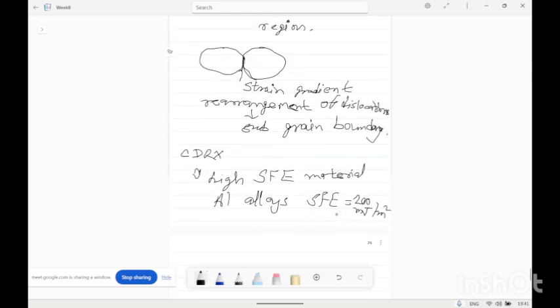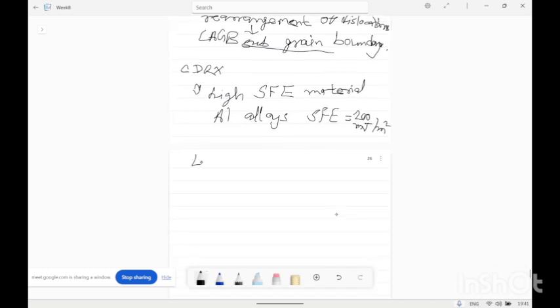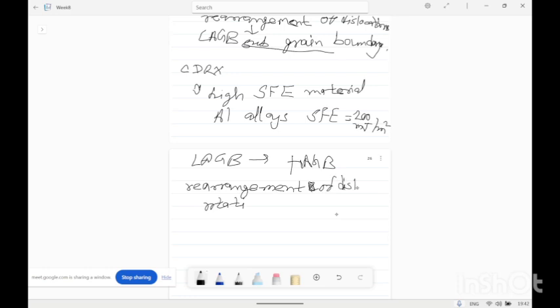So the subgrain boundaries formed in the discontinuous dynamic recrystallization have low angle grain boundaries. In continuous dynamic recrystallization, the low angle grain boundaries transform into high angle grain boundaries by rearrangement and rotation of dislocations. Rearrangement of dislocations and rotation of grain boundaries.